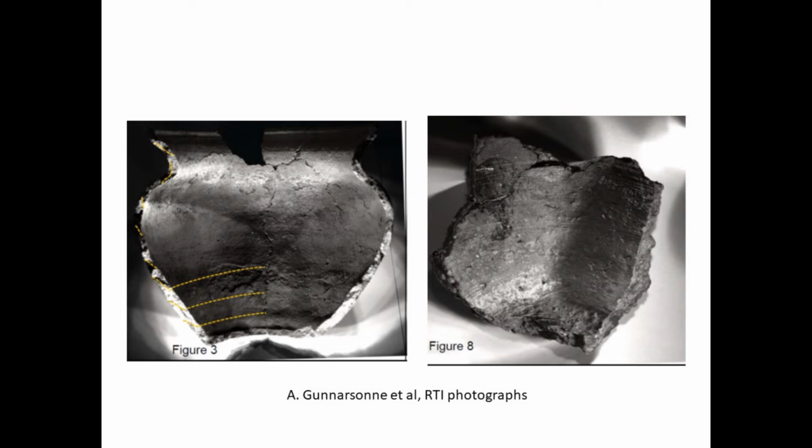According to the pictures and the very good photographs of the surface features visualized with the assistance of reflectance transformation imaging, it seems that in the two cases under study, rotary kinetic energy was used only at the finishing stage. I suppose so, because neither the internal nor outer topography presents significant deformation with rotary kinetic energy. The weak compression of the clay walls with rotary kinetic energy is expected to be visible in radial section. The coil mesostructure will be kept with very few subparallel voids.